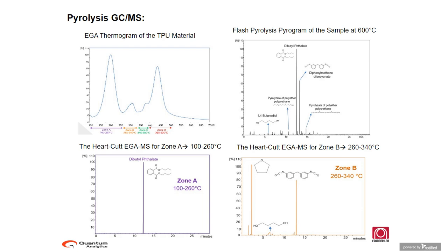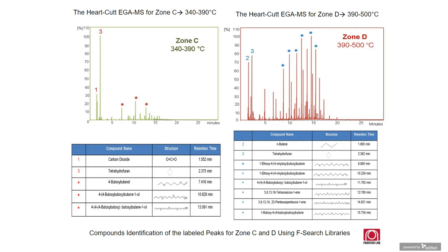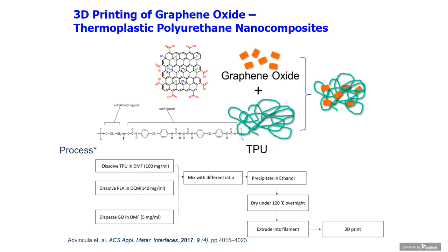But zone A, in particular, confirmed the presence of dibutyl phthalate, a plasticizer that we did not expect. And during hard cut at zone B, we confirmed the presence of this aromatic diisocyanate. And the zone C and zone D mass spec again confirmed the presence of various polyol compositions, which will enable us to confirm whether these were based on bio-based polyurethanes or other types of commercially available polyols. The bottom line is this type of confirmation, which we could have done with longer methods of deconstruction involving separation, solvent filtration, application of NMR, IR, etc., would have been tedious, and if not for GC mass spec pyrolysis, we would not have been able to use this material for our research.